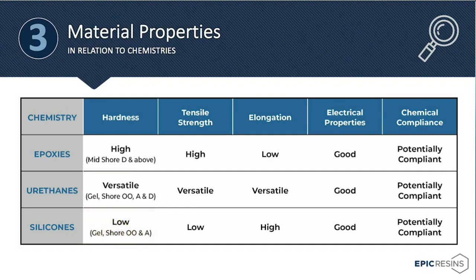Comparing the tensile strength of these three chemistries, epoxies are going to have the ability to have the highest tensile strength, again, coming from their ability to have the highest cross-link density. Urethanes have a versatility in tensile strength, again, because they have versatility in cross-link density. Silicones are going to have a low tensile strength, and again, that comes from their lower hardness and lower cross-link density.